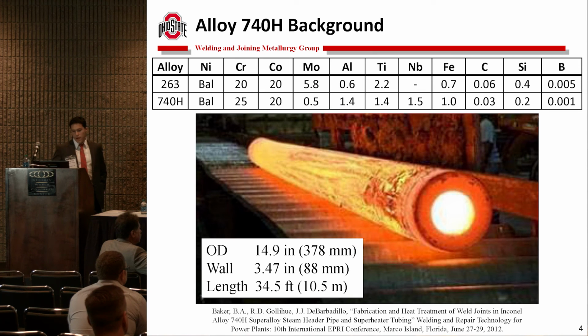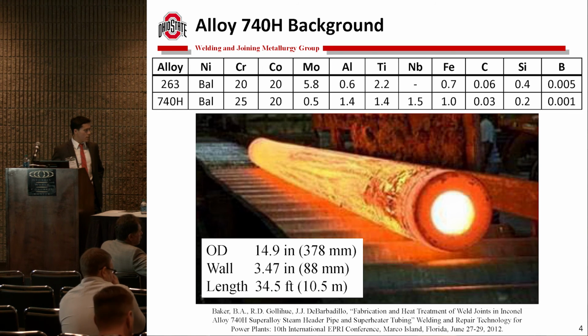This is a little bit of background about 740H as a leading candidate. I'll spend a little time on this. The starting point for the development of 740H was alloy 263, I think an older aerospace alloy, and this is the composition of alloy 740H. Important things to note are the low molybdenum, which helps with the fireside corrosion resistance I mentioned. I think molybdenum sulfides are susceptible to liquating at these temperatures. There's also a little bit of niobium, which will participate in the gamma prime formation. I think that is causing some problems for this alloy.